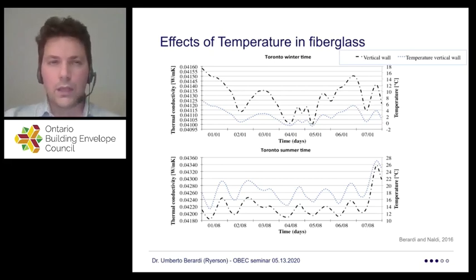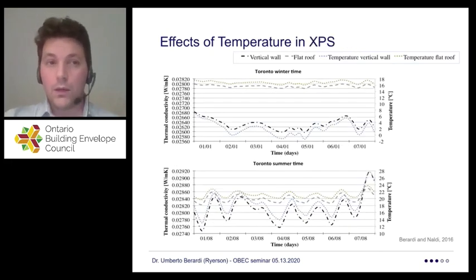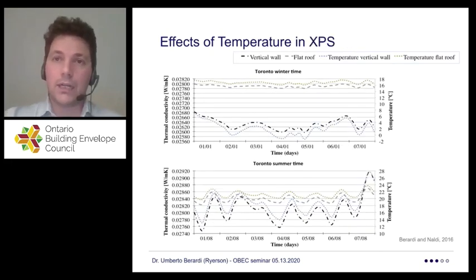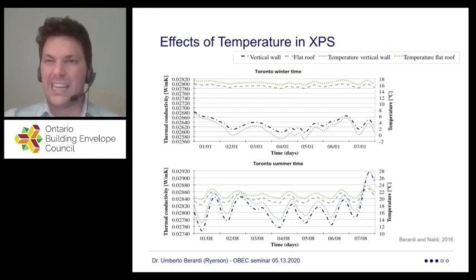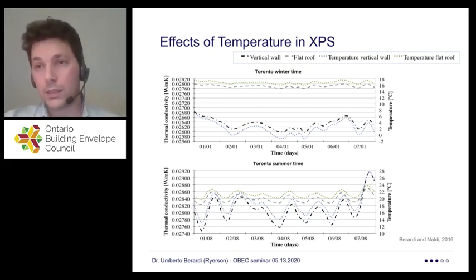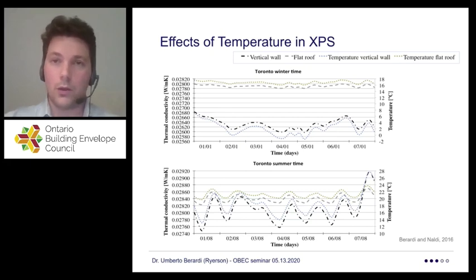If you see the y-axis, you see that the number is not really changing too much. So often this is not necessarily a big problem, temperature in isolation, when you look at fiberglass, or when you look at rock wool, or when you look at XPS. So there is a fluctuation in thermal conductivity because clearly the temperature changes. But in reality, the fluctuation doesn't really generate a huge difference in terms of its flux. And more importantly, typically in Toronto, winter and summer tend to overall compensate each other. So you get more flux in summer, a bit less flux in winter. You sum up all together this construction, and you more or less get the same kind of situation. Although this is still critical because you need to get a sense of condensation risk.